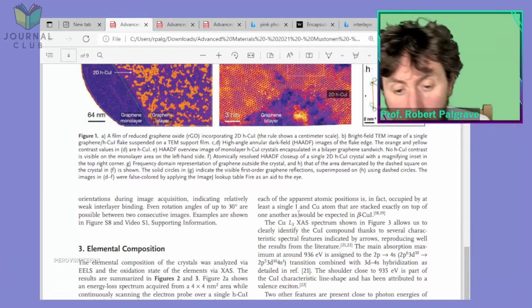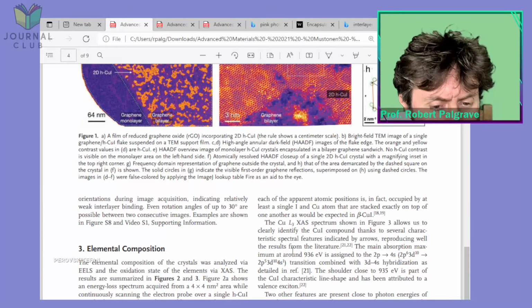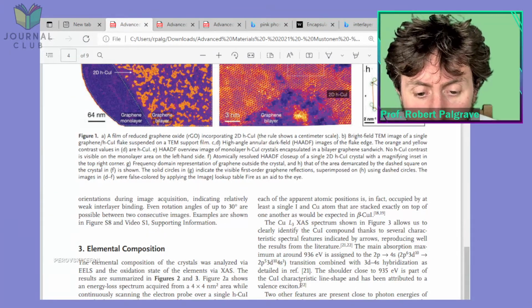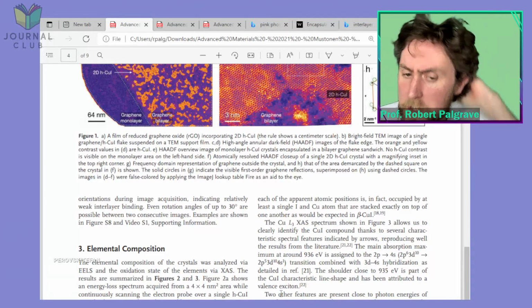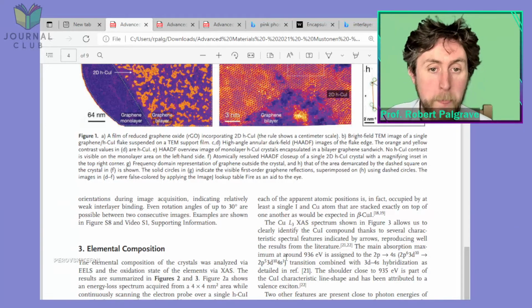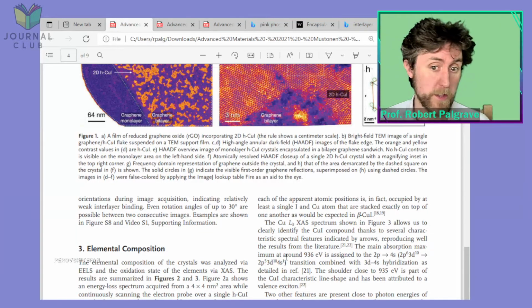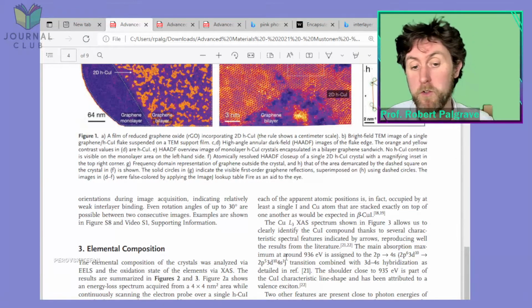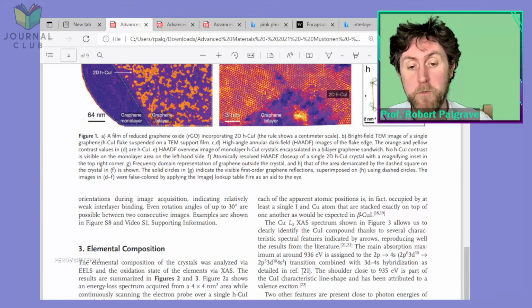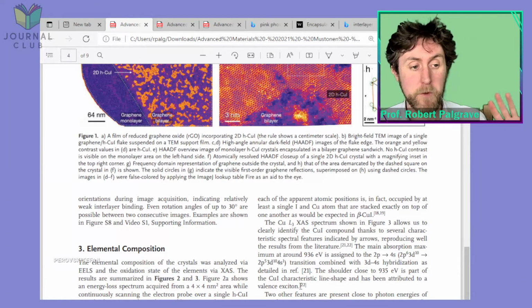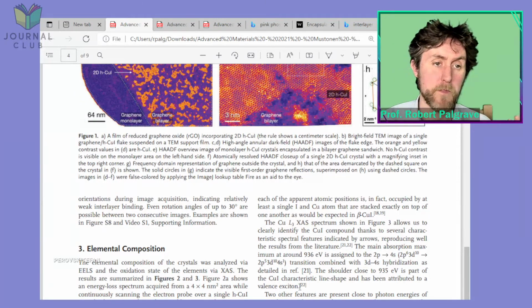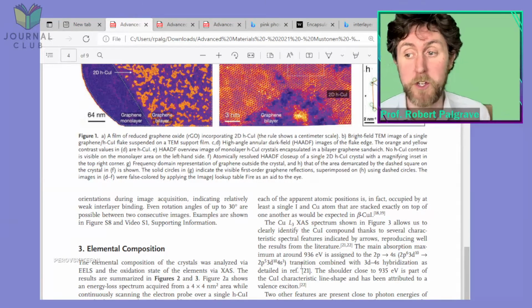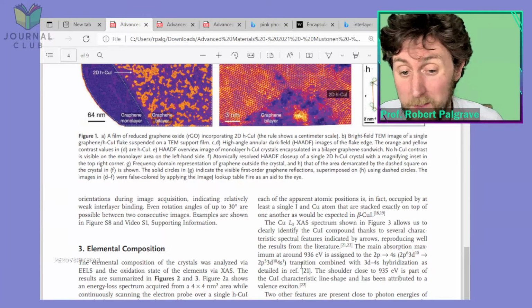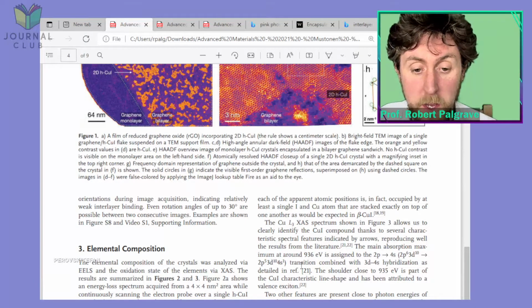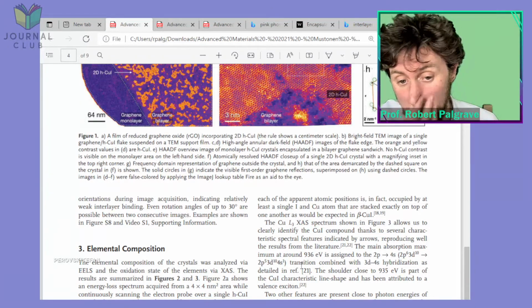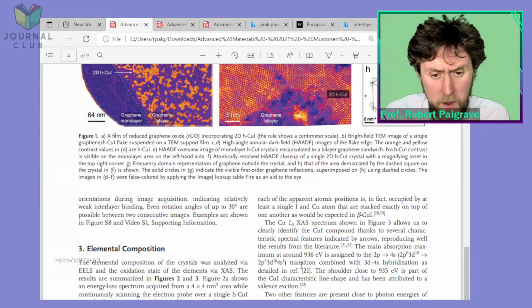valence exciton. Okay, interesting, because I wonder, following up on reference 22, you would imagine the excitonic structure is going to be very different in this 2D layered material compared to whatever else they're looking at. So I assume from reference 22, without having looked it up, because the paper we're looking at says they're the first people to make this 2D layered material, I'm assuming reference 22 isn't about this 2D layered material. It's probably about the standard cuprous iodide. So I would think, to be honest, the valence exciton, the excitonic structure, would be very different.